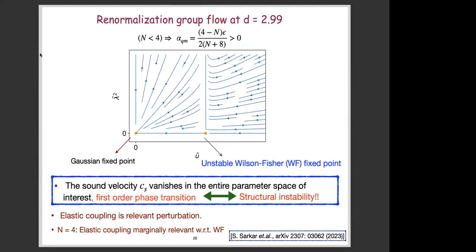Okay. So first, let's consider the RG flow at d equals 2.99, which is for a small value of epsilon. We are close to 3 dimensions, but not yet there. And n less than 4, that means alpha quantum greater than 0. So here I plot the RG flow in the lambda tilde and u tilde plane. What we observe is that we have a Gaussian fixed point, which is denoted here, and this is unstable both under this elastic coupling and this self interaction, because the flows are away from this fixed point.